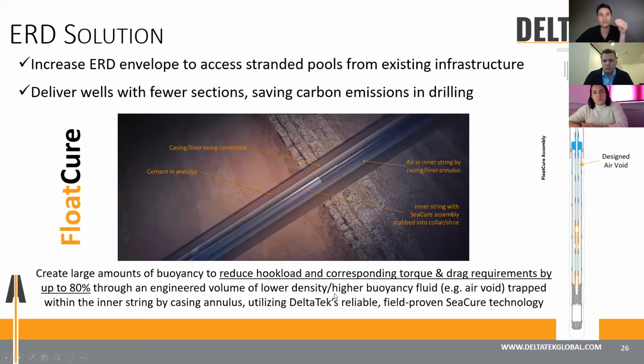The reduction in net effective weight of the string being cemented is in the order of 50 to 80%. So what that means is, typically say a 53.5 pound 9 5/8 liner might only actually weigh 15 to 20 pounds per foot. So when you consider the amount of additional reach that puts on the wells that are being drilled from existing infrastructure, you can suddenly grow your operational envelope from that platform by orders of magnitude.